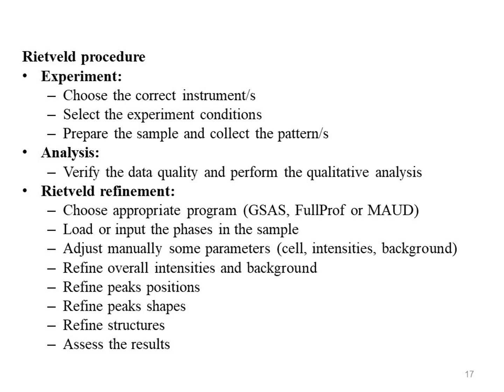Load or input the phases in the sample. Adjust manually some parameters like cell, intensities, background. Refine overall intensities and background. Refine peak positions. Refine peak shape. Refine structures. Assess the result.